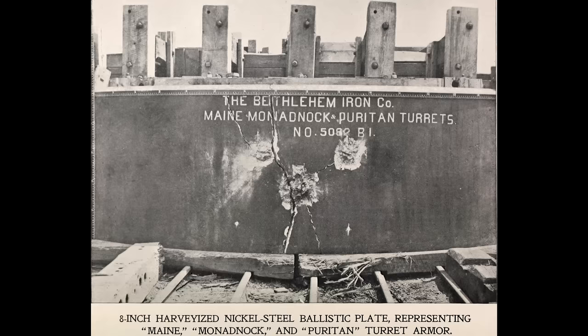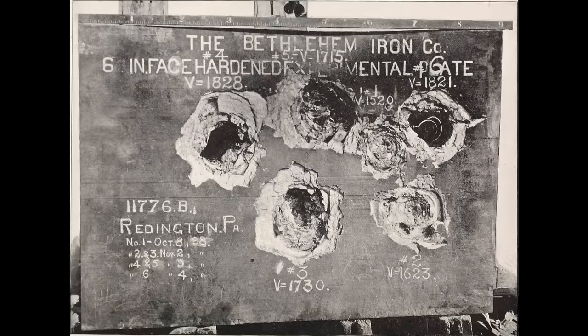This was obviously bad news for iron-hulled ships, and they very quickly were taken off of frontline duties, but when it came to implementing iron as armour, it presented a little bit of a quandary, because generally speaking, a hard, brittle material will need more energy to cause failure than a softer, more ductile material. But then, when that failure point is reached, the failure is far more spectacular and far more destructive.